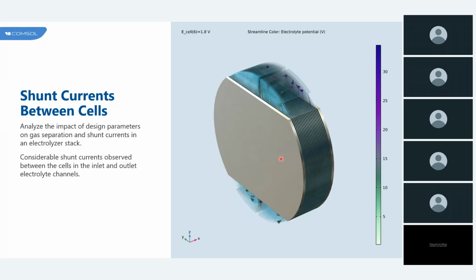forms. These results often show that the lower manifold and the channels are more prone to these losses, where the voltage gradients and flow paths overlap most aggressively. By adjusting the design parameters in the simulation, we can predict and visualize exactly where these losses occur, well before the physical testing. This enables engineers to redesign the manifolds, add insulation barriers, and mitigate the unwanted current loops. Ultimately, this improves the hydrogen purity, boosts the efficiency, and enhances the stack reliability.